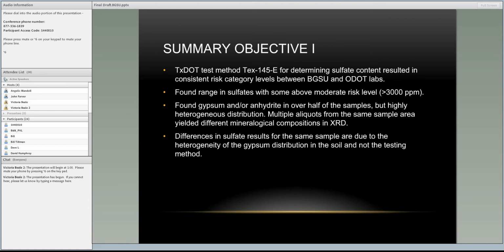With the soil samples, those are air dried for at least 3 days. We don't put them in an oven because we want to preserve any mineral structures, especially with ettringite or thaumasite. We don't want those structures to break down. And with the larger soil samples, rather than grinding it like you would for XRD or cutting it, I'd simply break off pieces of a larger piece and put it on the stub.